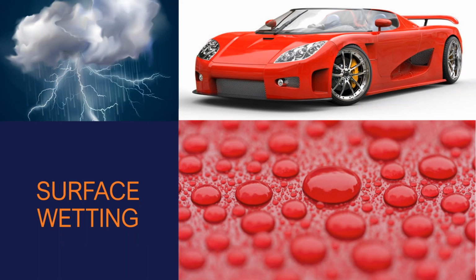Surface wetting. So what is surface wetting? Wetting means that the liquid flows and covers a surface to maximize the contact area and the attractive forces between the adhesive and the adherent bonding surface. For a liquid to effectively wet out a surface, the surface energy of the adhesive must be as low and usually lower than the surface energy of the adherent to be bonded. Alternatively, the surface energy of the substrate must be raised to fulfill the bonding.